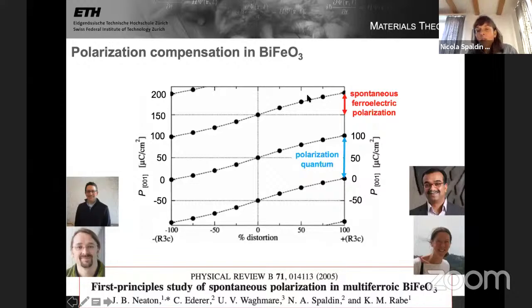And as we distorted the bismuth ferrite to its ground state ferroelectric structure, it evolved from a value of, say, minus 50 to a value of 0. The spontaneous polarization, the switchable bit, is this part here. And you see that's the same, whichever branch of the polarization lattice we go along. As I mentioned earlier, this was an important result of the modern theory of polarization.